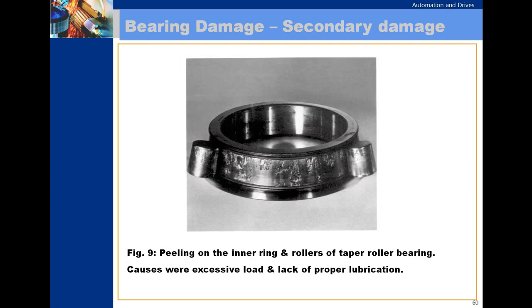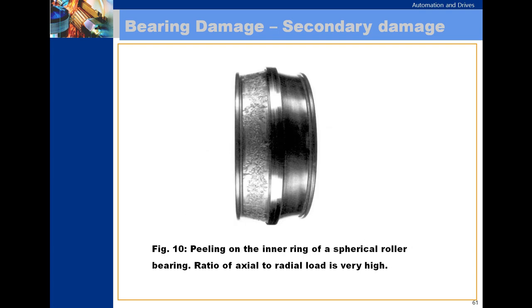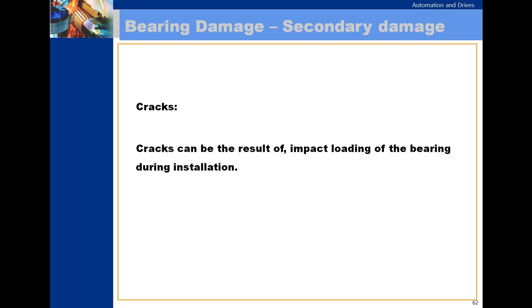Progressive stages of peeling. Peeling on the inner ring and rollers of a taper roller bearing is caused by wear, excessive load and lack of proper lubrication. Peeling on the inner ring of a spherical roller bearing occurs where the ratio of axial to radial load is very high. Cracks. Cracks can be the result of impact loading of the bearing during installation.